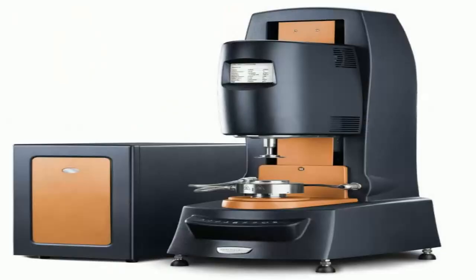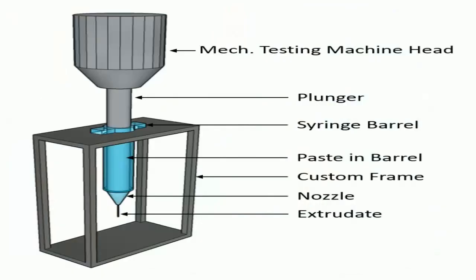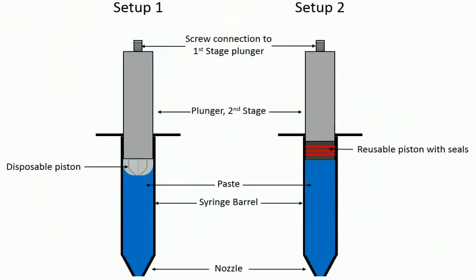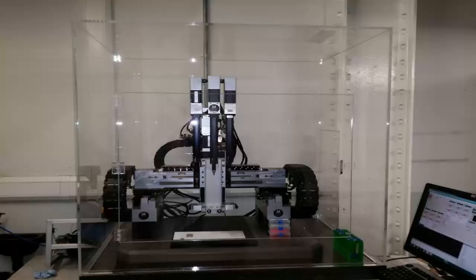The source material points to a specific ingredient that plays a key role in some of these pastes, pluronic F127 hydrogels. And there's something really surprising about these. This is one of those genuine aha moments from the research, I think. Pluronic gels exhibit what's called inverse thermal gelation, meaning they are liquid and easy to mix when they are cold, but they turn into a gel and become stiff when they warm up, usually right around room temperature or body temperature. Wait, hang on. Liquid when cold, gel when warm? That's completely backwards from, like, jelly or soup. It totally is, and it's absolutely brilliant for processing these ceramic pastes.